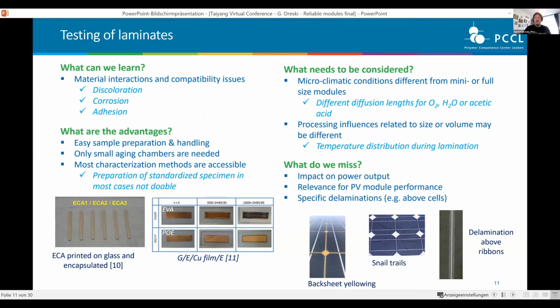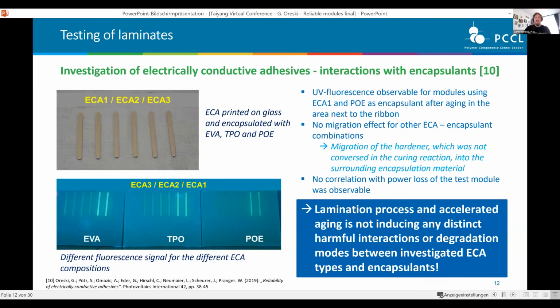One example, what we did a few years ago, we tested whether there are interactions between electrically conductive adhesives used for replacing the solders in ribbons with different types of encapsulants. So we just screen printed these 3 ECA types on glass, encapsulated them, put them in some weathering chambers, and what we found out, yeah, in most cases nothing is happening.